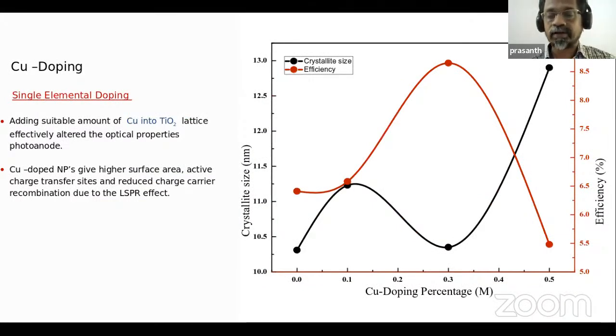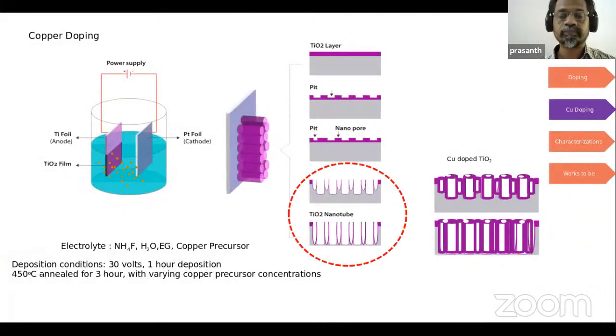So if you're doping the material, the crystalline size will also change. With that, the efficiency shows an optimum crystal size for making a high efficiency value in this material. And again, the copper doping also can be done with a simple electrochemical method. That is an advantage. That makes the system fabrication very cost effective and simple. And if you want to scale up, you can go with a bigger chemical bath system. So that is a major advantage of working with an electrochemical system.